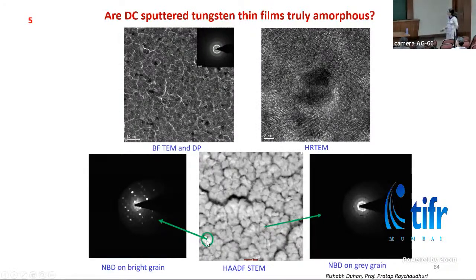And here is what will be seen as a bright speck in the STEM image. When we take the diffraction pattern from this spot, we can see that it has nice spots. That means this particular bright contrast is crystalline material. When we collected a diffraction pattern from the gray region, it matched an amorphous region. So that means we can study the crystallite inclusions in DC sputtered tungsten thin films.